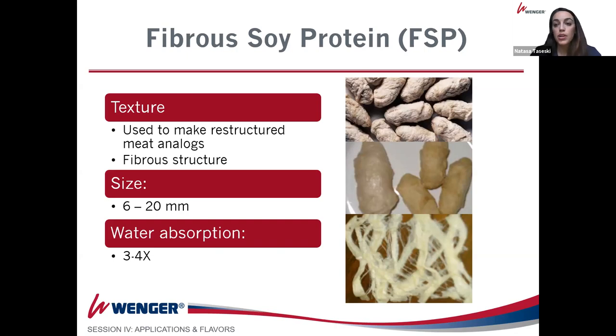The sizes of this product also vary. You can go from 6 to 20 millimeters, and typical water absorption is about 3 to 4 times the dry weight.